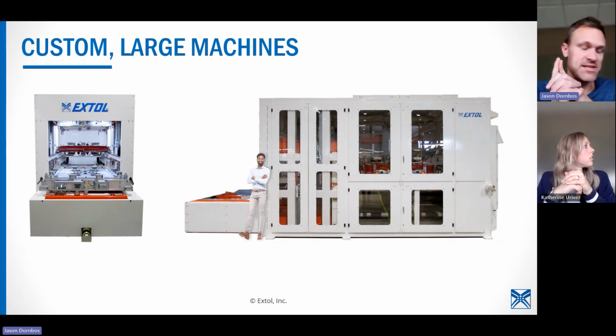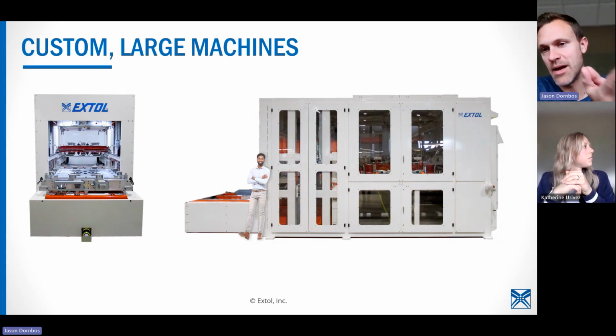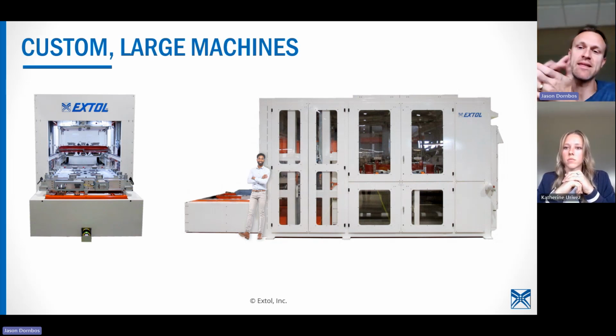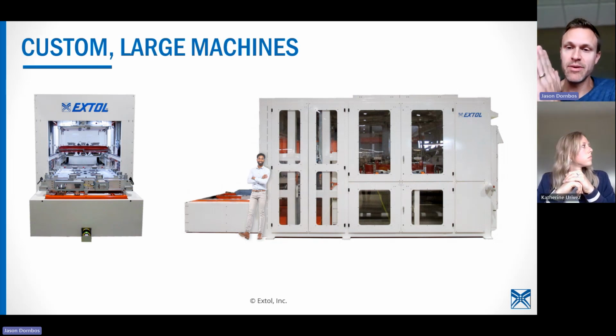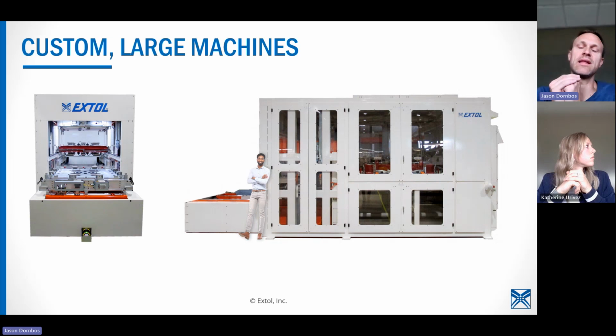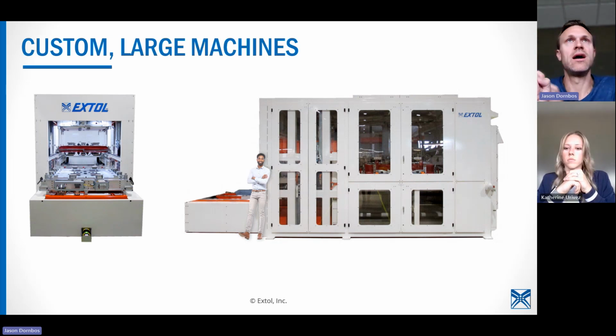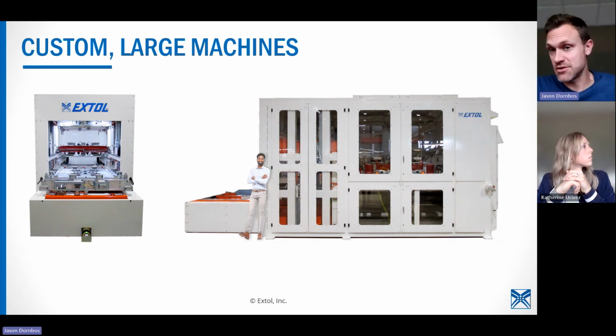Okay, so now you're getting to something that's very important. So the open time, after you've melted your parts, you've put a bunch of heat into them. As soon as you come off of that heated tool, they're cooling off. And we want to make sure that we get those parts back together so that they can weld before we lose too much heat. If you start to lose too much heat, that top surface can get skinned over. You get a cold weld when that happens, and that results in leaks and poor strength. So typically you want a quick open time, as fast as your machine can go for the open time. And we'll see some more examples so you can get an idea about just how long that is.